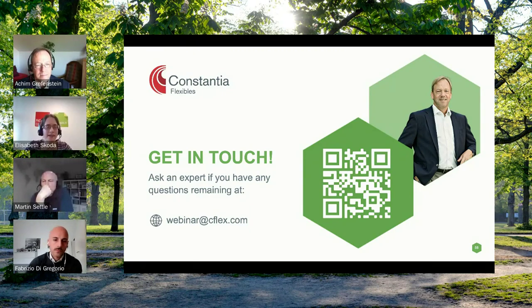Thank you, Fabrizio. And somebody wants to clarify on the subject of monomaterials and is asking, when you say monomaterial, do you really mean with no additives whatsoever? Maybe one for you, Achim. When we talk monomaterials, then of course we need some additives, alone the inks, adhesives, and barrier layers are non-polyethylene or non-polypropylene. So therefore, in most applications, we achieve a PE or PP ratio of more than 90%, and in thicker packaging, also higher than 95. It mainly depends on the total thickness of the pack. If you take a very thin crisp pack out of two BOPP films with just 40 micron, and you have five gram of inks and adhesive, then of course you can be happy if you're above 90%. While in a thicker pack of more than 100 micron, you are above 95. Yeah.